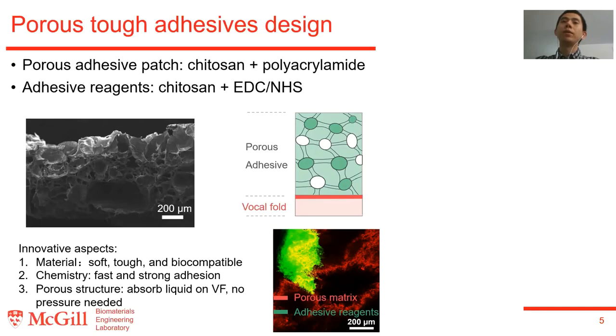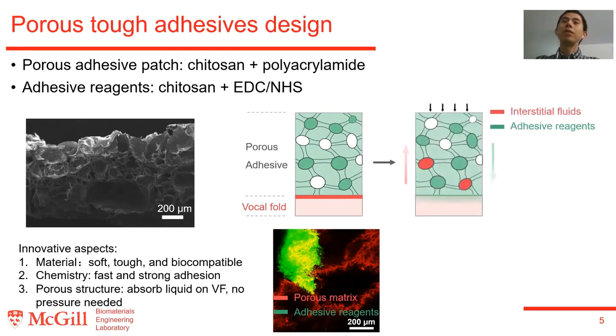In the fluorescent image, the red signal is the porous hydrogel and the green signal is the adhesive reagents. When this hydrogel patch is put on top of the hydrated vocal fold tissues, the open pores inside the adhesive can uptake the interstitial fluid and form an instant dry adhesion with the tissue. After that, with slight or even no pressure, it will release the adhesion reagents to the interface and bond with the vocal fold tissues.